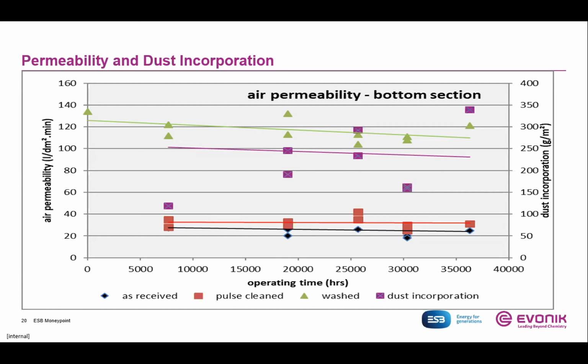The next interesting chart, or let's say not exciting chart, is this one here, where we could compare over several investigations. We started at 8,000 hours, and we had a really good record of this filter unit. We could not see any big change in the air permeability. This is a good indication that there is overall no dust penetration, and also no big clogging of the filter cake forming a crusty cake. This again confirms, with the quite steady dust incorporation, that the performance of the filter bag is by far not tending to some limiting lifetime expectation for this set of filter bags.